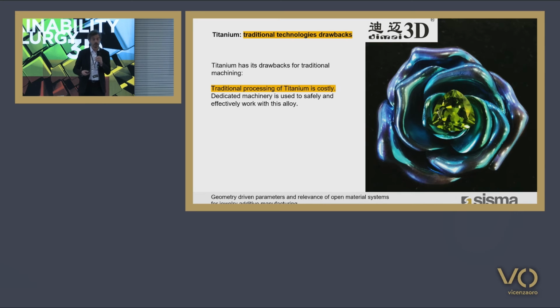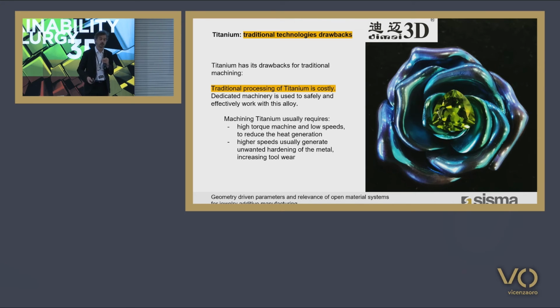We focus on titanium because it's difficult to machine and process with traditional technologies. Traditional processing of titanium is really costly. Machining is really difficult and could also be dangerous sometimes. For those of you that work a lot with milling machines, you know that with titanium you need to slow down the speed of milling in order to avoid unwanted hardening of the metal. So machining is slow.